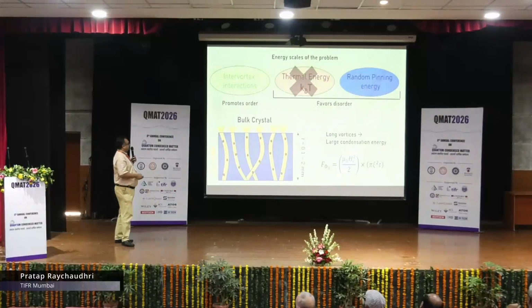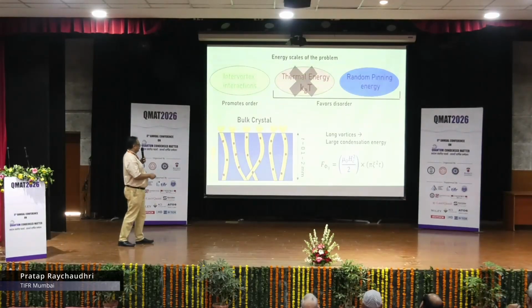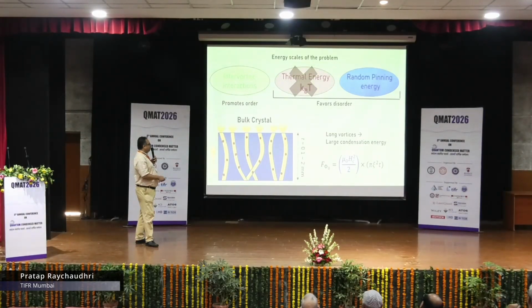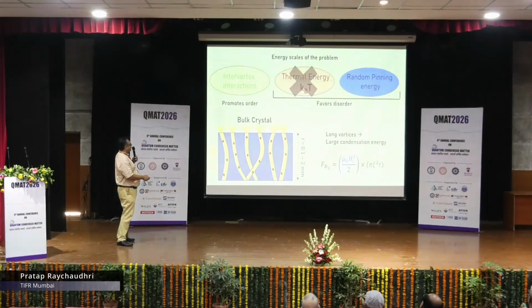Why is that? Because when you take a crystal, you have a thickness of the crystal which is about, let's say, 0.1 to a few millimeters. And then if you calculate the condensation energy of the vortex for such a long vortex which is passing through the superconductor, you can calculate that this quantity will happen to be much larger than kT. So the vortex actually does not jump from side to side.